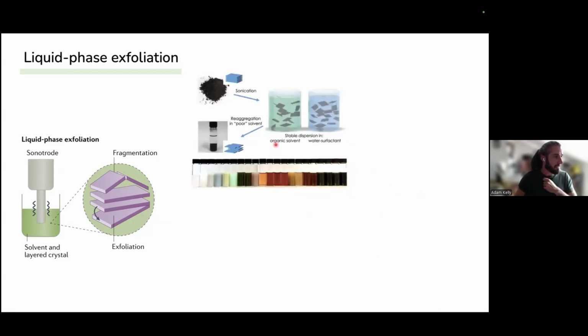So when you do this in a dispersion that is an organic solvent or water with surfactant, we can produce stable dispersions of nanosheets. However, if we use solvents like pure water, for example, with graphite, this is badly matched. So all your material will just crash out and it's not stable.